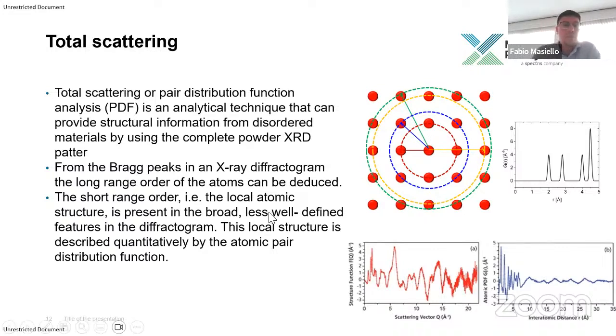Like I mentioned before, from the Bragg peaks in a diffractogram you get the long range order of the atoms, and the short range order, the local atomic structure, is present in the broader, less defined features in the diffractogram. By using the total scattering technique, you can get the local structure. It's represented here, where you get intensity peaks in your total scattering curve at certain positions where there are atoms in your local order.